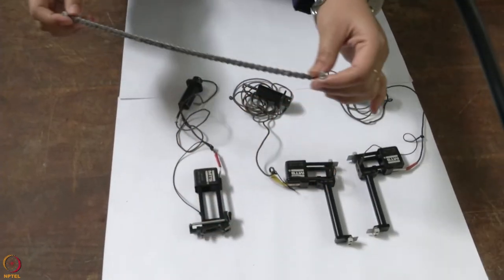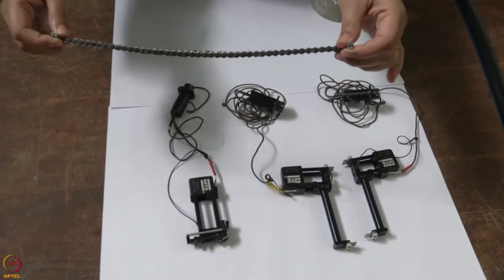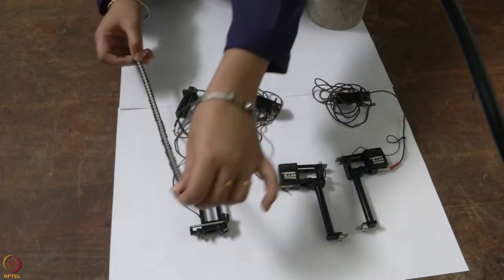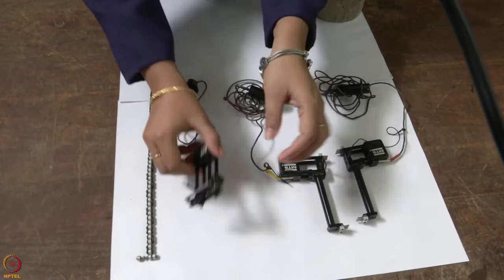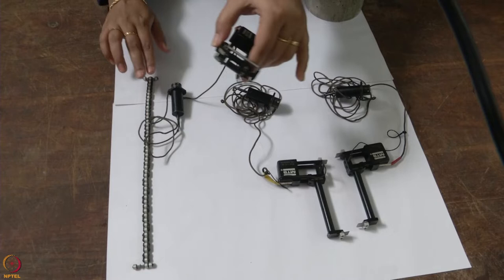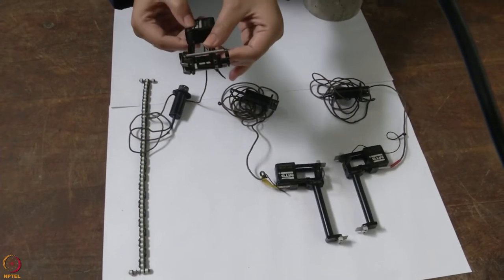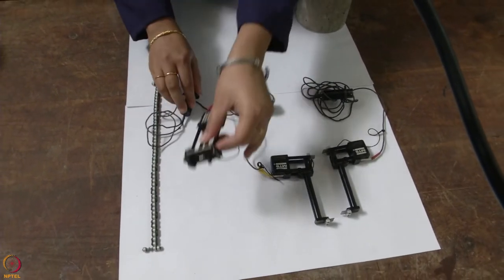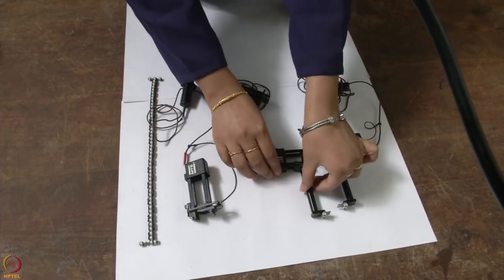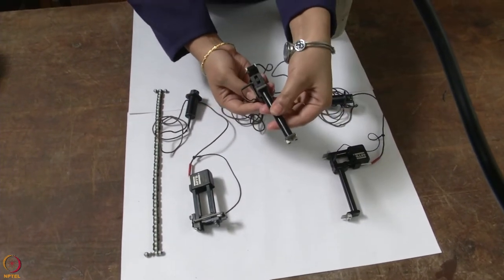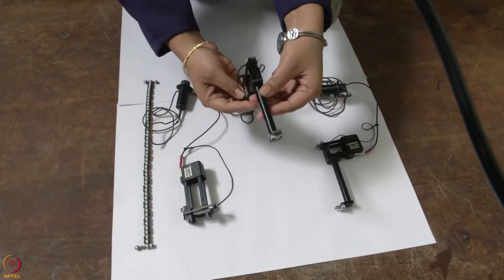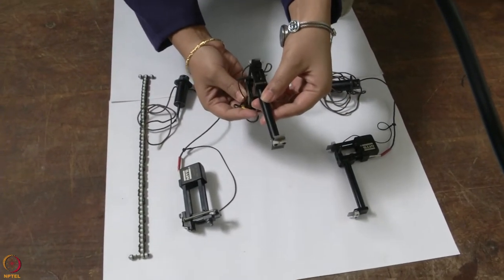We have an undeformable chain which will be placed around the specimen, and an extensometer will be connected to this chain to record the change in chord length. We have two axial extensometers which will record the axial deformation of the specimen.